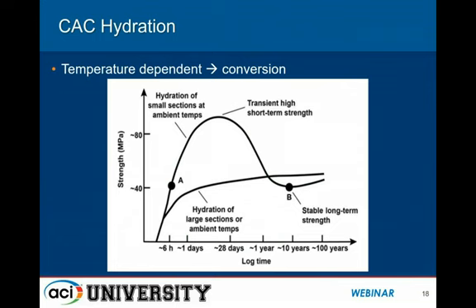In the alternative configuration, we see in the lower curve on this chart a large section that hydrates, in which heat builds up in the concrete. And in this case, the conversion process is bypassed. So we have two different types of behavior that can potentially be seen depending on the temperature history. And that's important in a lot of ways.